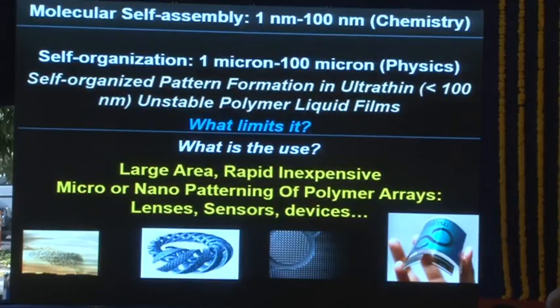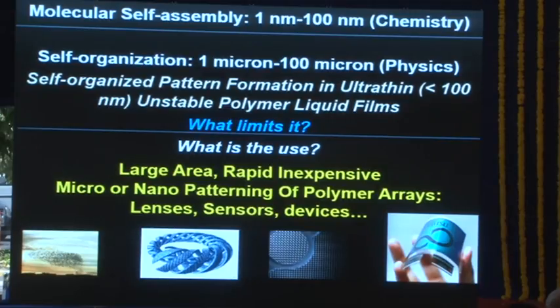And the reason for that is that when you deform something, when you change the shape, you increase the area. When you increase the area, the surface energy of the system increases. So you have to put in a lot of work in that system in order to increase the area. When you do it on a small scale, because you don't have that much work available per unit area, the deformation is on a large scale, a micron scale, but not nanometer scale. In other words, if you take a surface and you create a dent in it every nanometer, it'll require a lot of energy from outside, right? And focused energy on that point. Because that doesn't happen, you basically create a surface which is undulating on micron scale rather than nanometer scale.